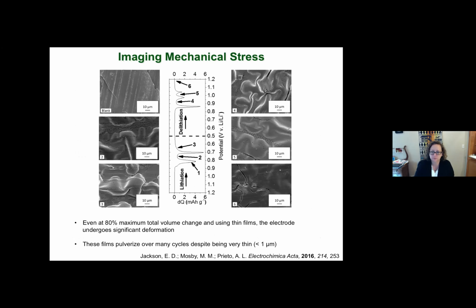We can also image thin films of this compound, and I'm showing you this because I know there are a lot of mechanical engineers listening. The mechanical stresses in dense anodes like this one, like silicon, and for sure the plating and stripping of lithium metal are quite challenging.